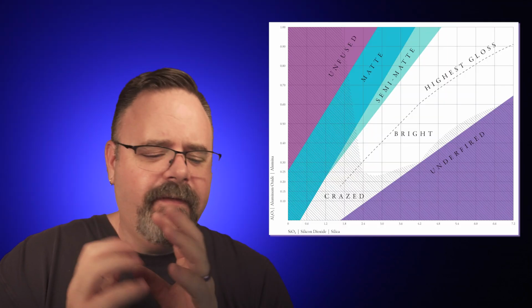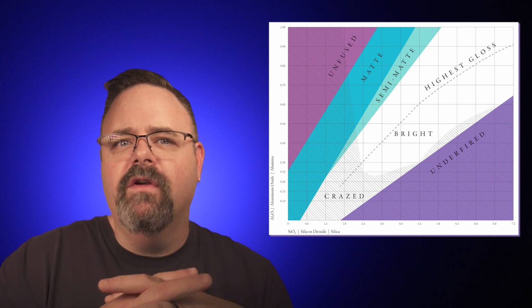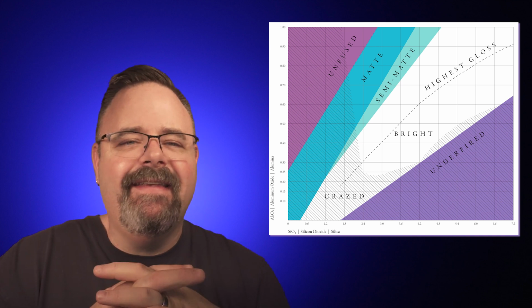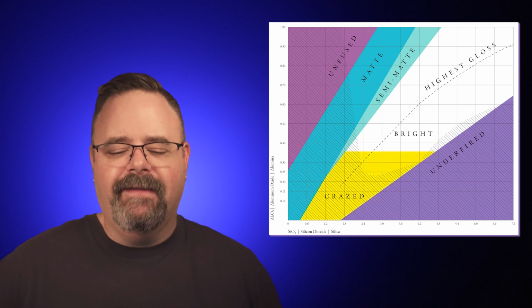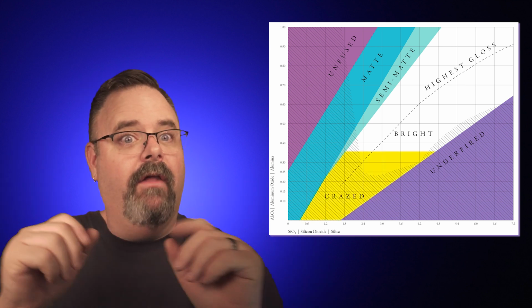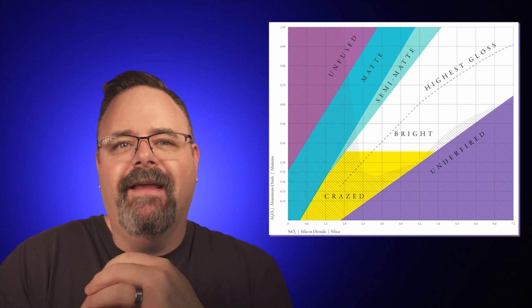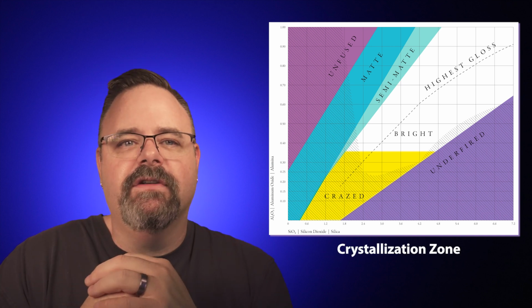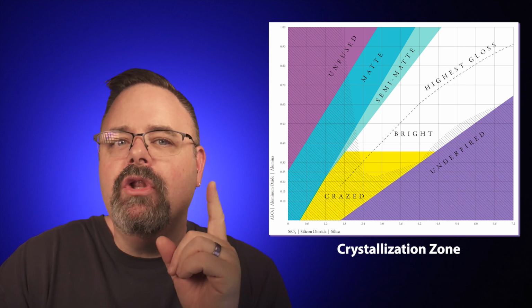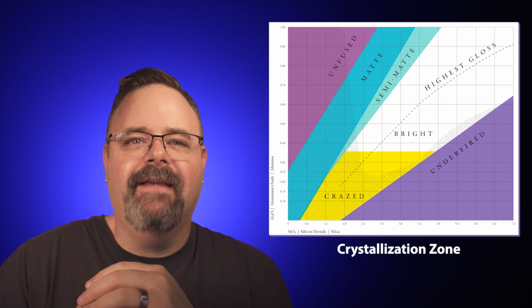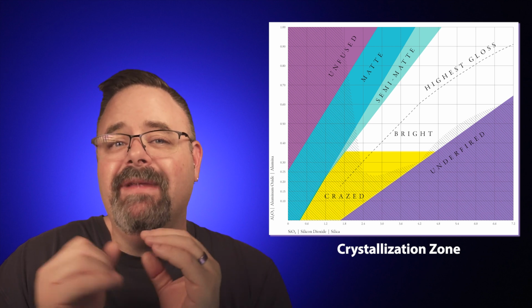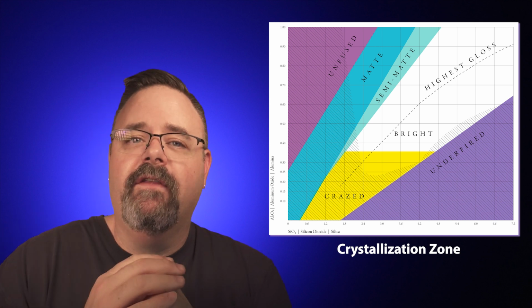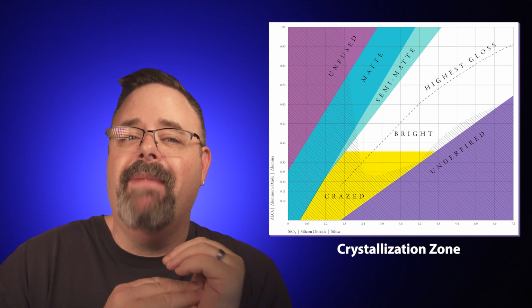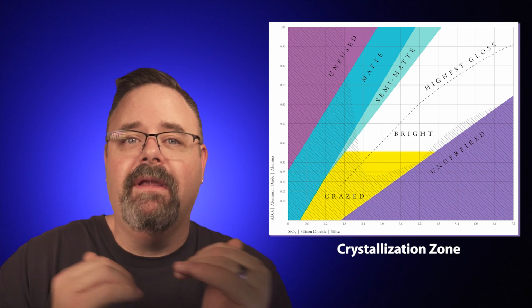The next thing you need for a crystalline glaze is that you need the right chemistry. And that means, where does it fall on Stull's map? This is a very important distinction, and this is something that my wife Rose and I discovered in our research, that in fact there is a secret region on Stull's map where all crystalline glazes exist. The zinc ones, the calcium ones, the magnesium, some other ones we'll talk about in another video, but all crystalline glazes exist down here in what we call the crystallization zone, which is very low on the map in the glossy section, not in the matte glaze section. And that is a really, really important distinction, because it's the different chemistry of crystal that's forming in a crystalline glaze with some different variables than matte glazes. And understanding the difference is going to be a huge deal.